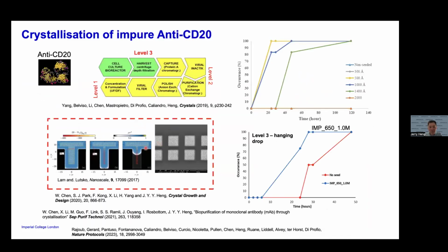We spent a little while, but with input from collaborators, and I do appreciate a lot of work that excellent modelers and computational scientists have guided our experimental work. This is work from Jim Lutsko and Julian Lam, who demonstrated a certain specific pore dimension was ideal for the nucleation or crystallization of anti-CD20. We went about doing that. So we drilled holes. These holes were 60 nanometers. We called them Imperial 650.